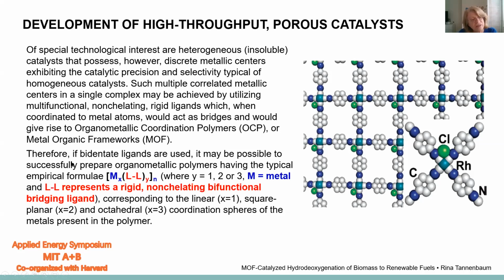And so what we concentrated on was bidentate ligands. That means ligands that have two functional groups. With those, one can prepare organometallic polymers or coordination polymers that have the typical empirical formula of Mx(L-L)y, L being the functional group, and it's a polymer, so it's a network, where y is equal to 1, 2, or 3, M is the metal, and LL represents these rigid, non-chelating, bifunctional bridging ligands. And so if y is equal to 1, then we're going to have a linear polymer. If y is equal to 2, we're going to have a square planar geometry, and an octahedral geometry with y equals 3. So coordination spheres are going to be according to the nature of the metal itself.